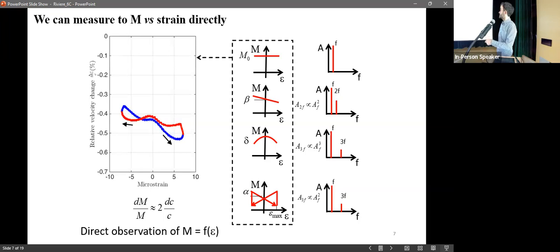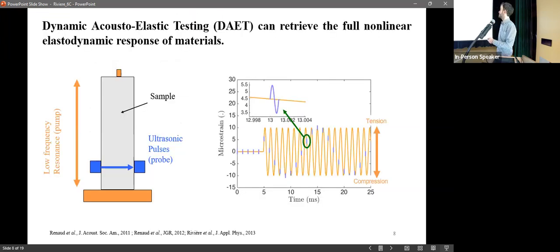And so this is an example of what we're able to do. We are able to measure the change in velocity as a function of strain here. And the changes in velocity are proportional to the change in elastic modulus. And we do this using a technique called dynamic acoustoelasticity. So it's a pump probe method.